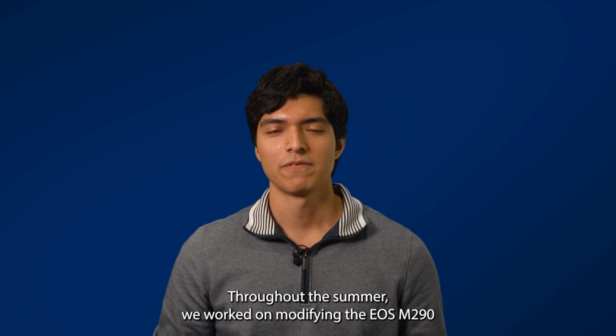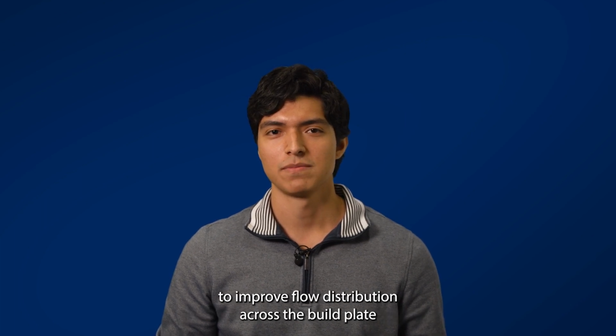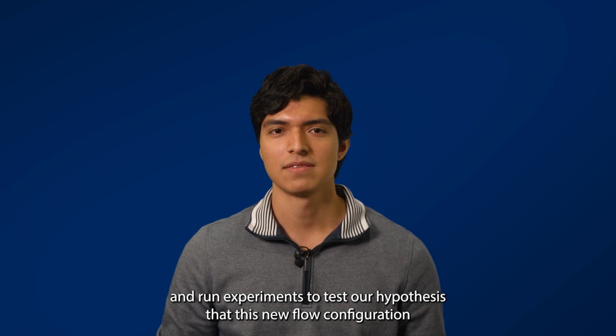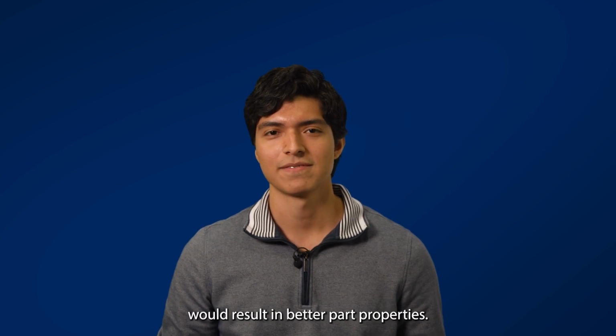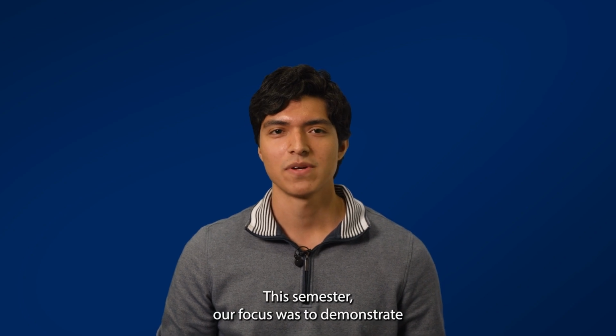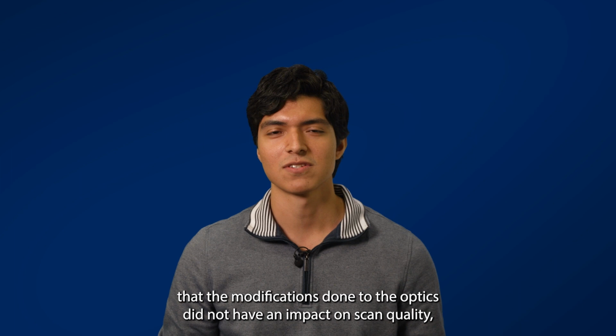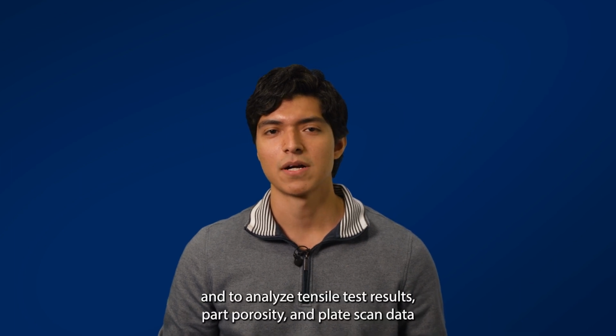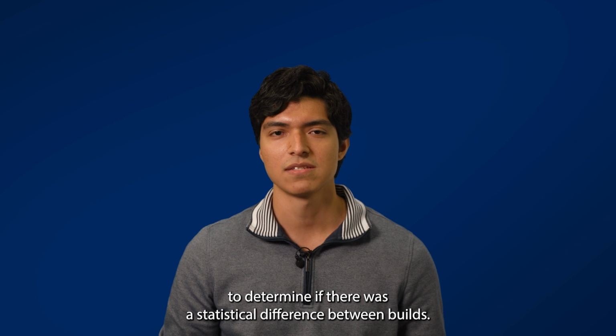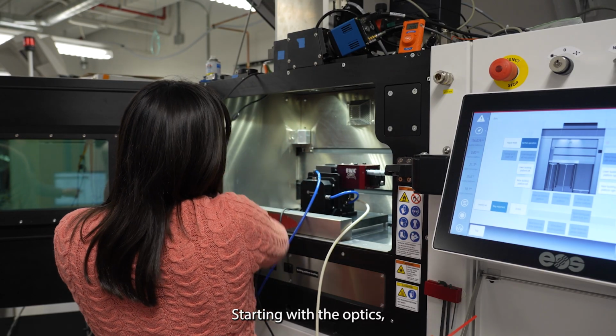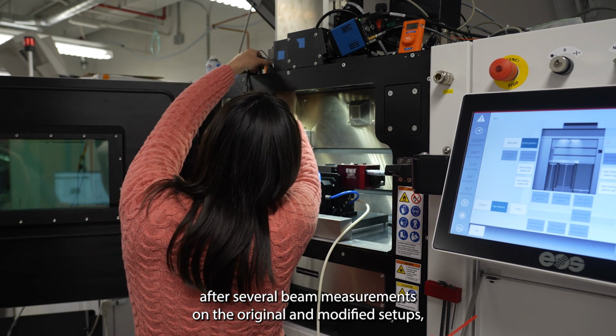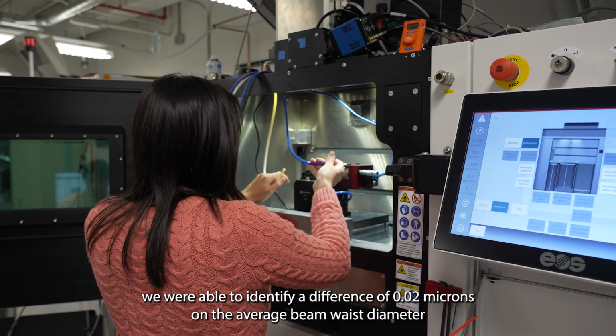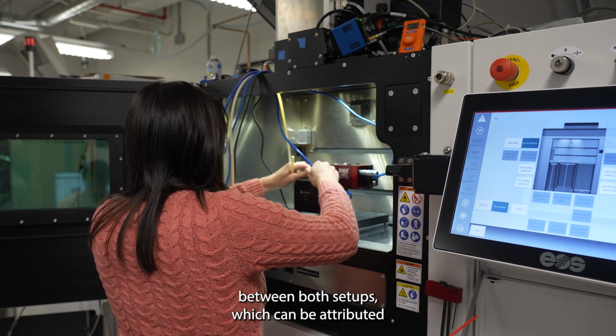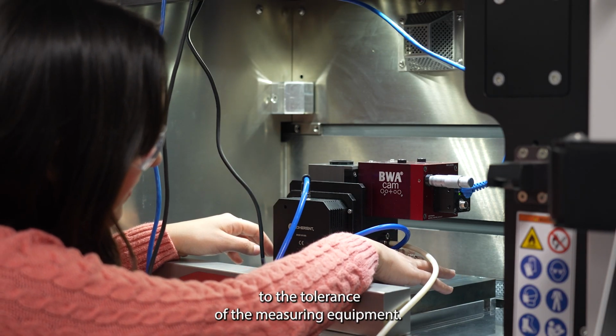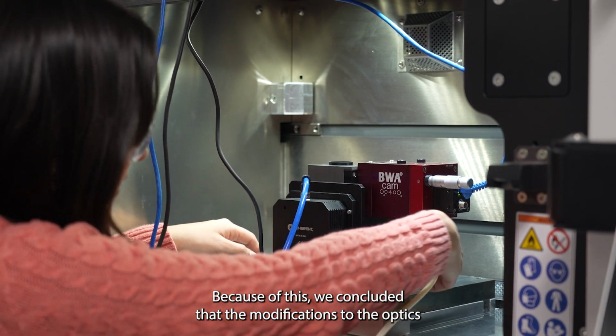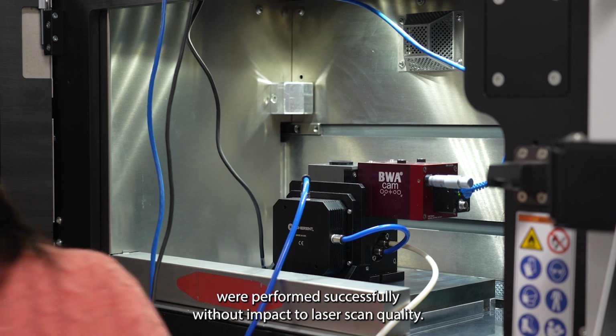Throughout the summer, we worked on modifying the EOS M290 to improve flow distribution across the build plate and run experiments to test our hypothesis that this new flow configuration would result in better part properties. This semester, our focus was to demonstrate that the modifications done to the optics did not have an impact on scan quality and to analyze tensile test results, part porosity, and plate scan data to determine if there was a statistical difference between builds. Starting with the optics, after several beam measurements on the original and modified setups, we were able to identify a difference of 0.02 microns on the average beam waist diameter between both setups, which can be attributed to the tolerance of the measuring equipment. Because of this, we concluded that modifications to the optics were performed successfully without impact to laser scan quality.